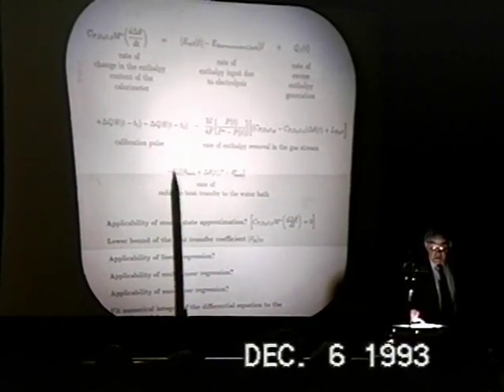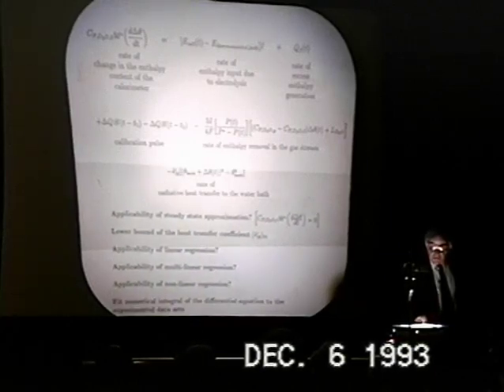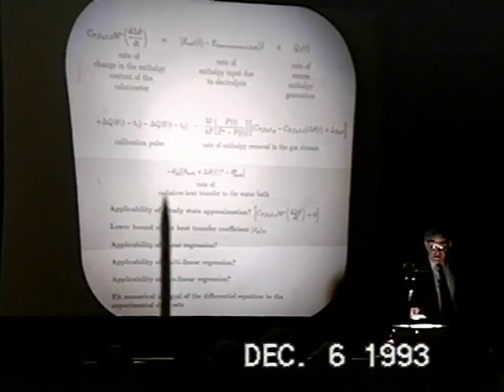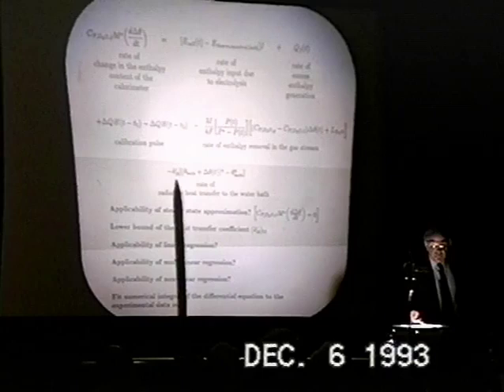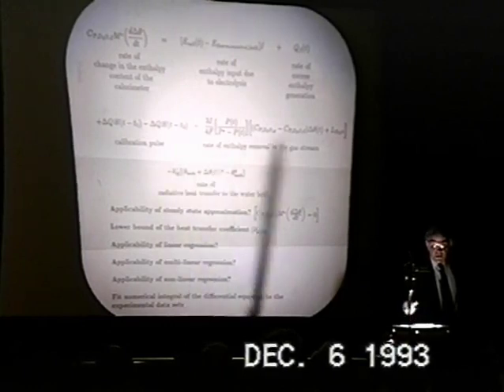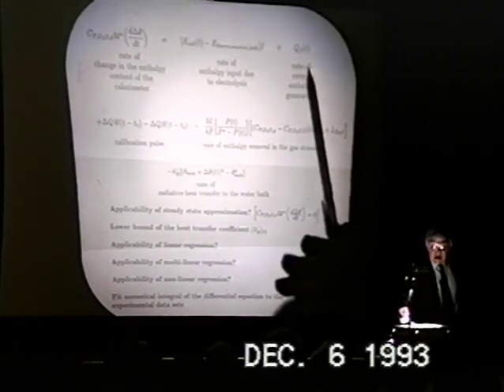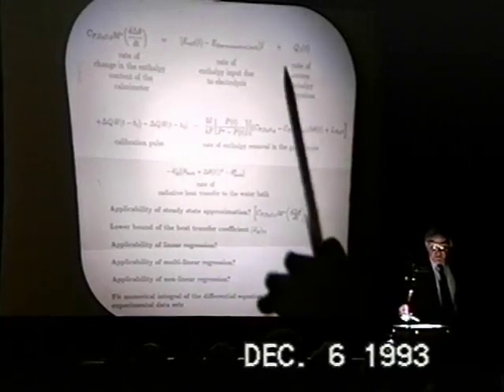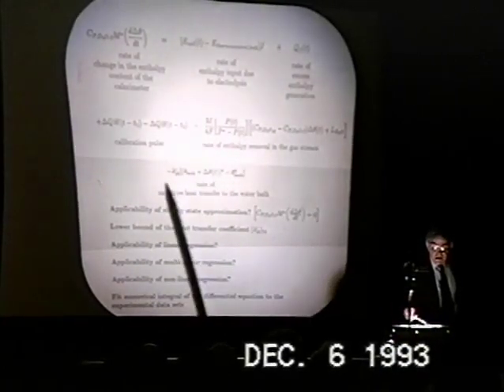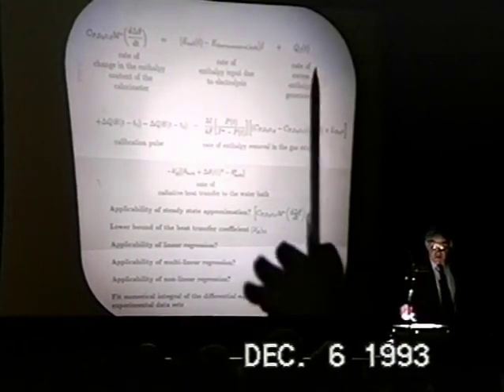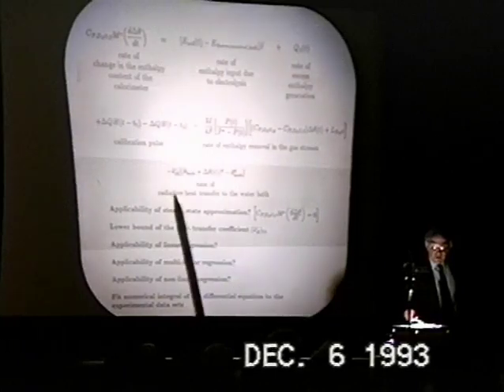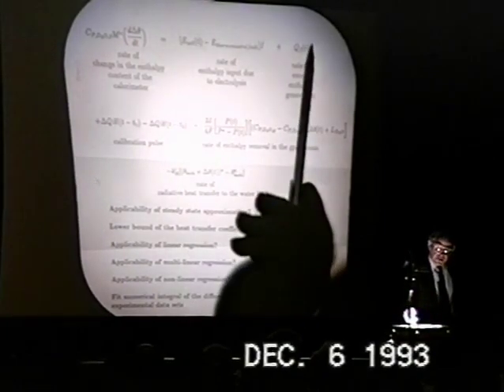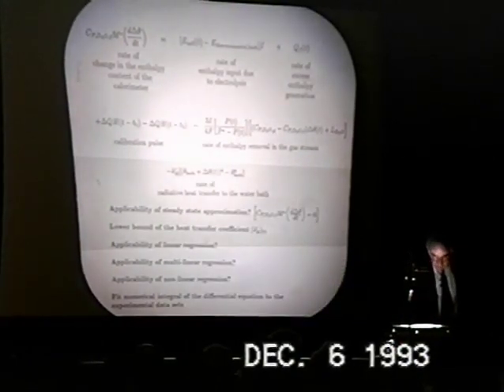And for blank experiments, you find that this turns out to be the true heat transfer coefficient. But if you do the palladium deuterium or palladium alloy deuterium D2O system, then you find that this is always less than the true heat transfer coefficient. And moreover, the time dependence of this heat transfer coefficient shows you that progressively you build up an excess enthalpy term. It's a lower bound, because of course if you evaluate this coefficient from this equation, putting this in at zero, then you will get the minimum value of this heat transfer coefficient. And you can have such a high rate of generation of heat that this actually becomes negative.